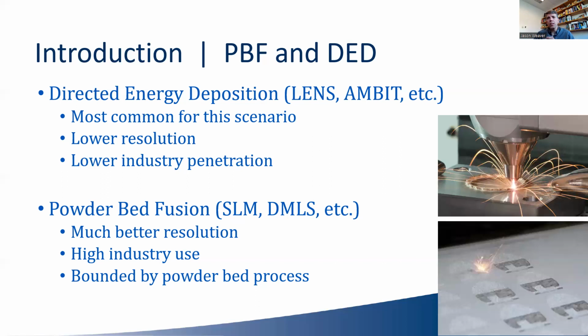This is becoming very standardized in industry. There are a lot of locations where you can do this process. It has much better resolution. You can get really fine details. It's fully dense metal. But we are limited for this scenario because we're using a bed of powder. So we're typically starting at the ground level with no existing material and building on a metal print bed surrounded by powder. And so even if we were building on an existing part, that part would have to have a very level flat surface, and then we're building up in the Z direction from that.